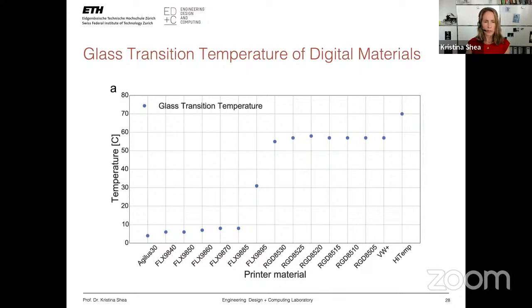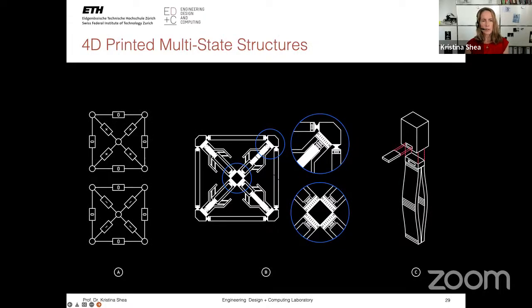And we got a little bit lucky because these are the materials of the printer. And it turns out that the soft materials are down here. They have a low glass transition temperature. Then we have this one point of 30 degrees in the middle. And then we have a group, the rigid materials, with a higher glass transition temperature. And so this is beneficial in the design to be able to use these different properties. So here's the design again. And so you have these bistable actuators that can be actuated by the shape memory polymer strip. So they can be actuated, pulled out or pushed in. And then 0 is just the structure around, so it's not changing state.